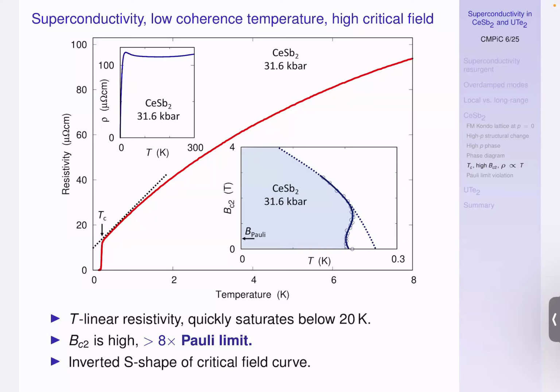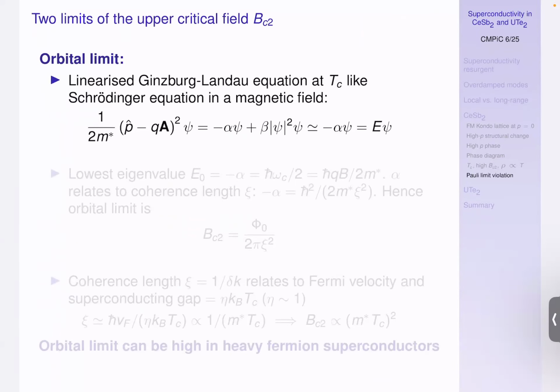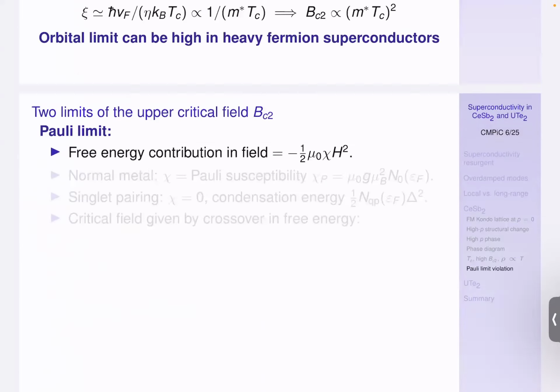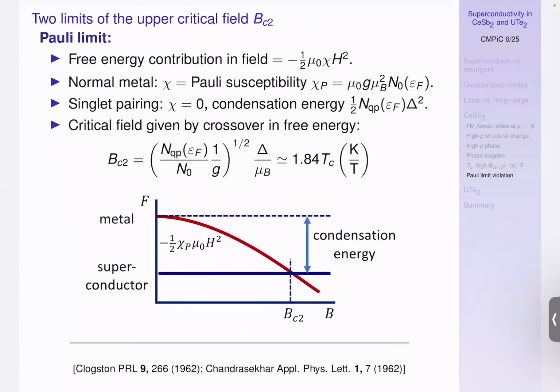There's also this strange shape of the curve, this S shape, which is kind of surprising. We think it may just be explained by the fact that we are just inside the antiferromagnetically ordered part of the phase diagram, and when you apply a field, you're not just suppressing superconductivity, you're also affecting the magnetic order. This S shape goes away at higher pressure, when the antiferromagnetic order is gone. Okay, so I only have 10 minutes left. Maybe I should skip the theory part. I was hoping to explain orbital limiting, but let's just look at the Pauli limiting.